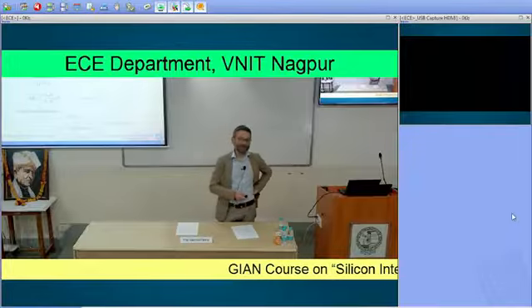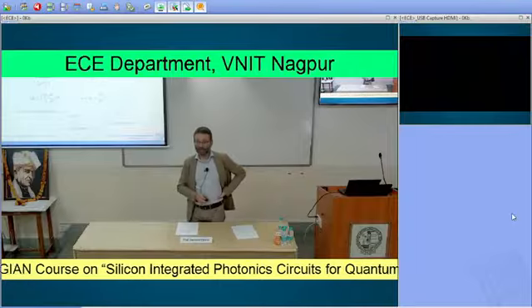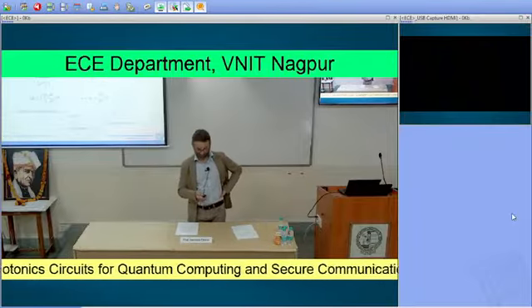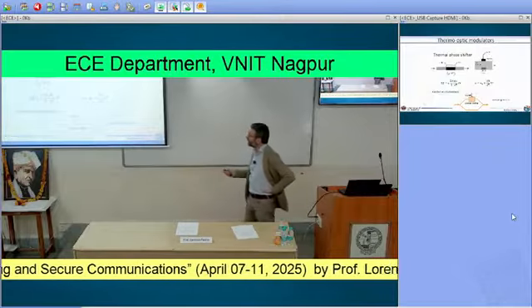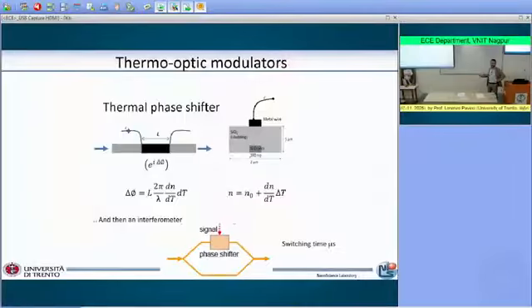So the first one is based on thermo-optic modulators, which is a technique that is very cheap and easy to fabricate, and this is one of the techniques that we are also using a lot. What you have here is your silicon waveguide, a very small core silicon waveguide where the light is traveling through. And then you have the silicon oxide cladding, and you can notice the numbers here. The silicon waveguide is 500 nanometer wide and 200 nanometer thick. And then on top of the silicon core, we have a silicon oxide cladding, and typically the thickness of this cladding is 800, 600, 1 micron. So it's thick. And then what you do is deposit on top of the silicon oxide a metal wire.